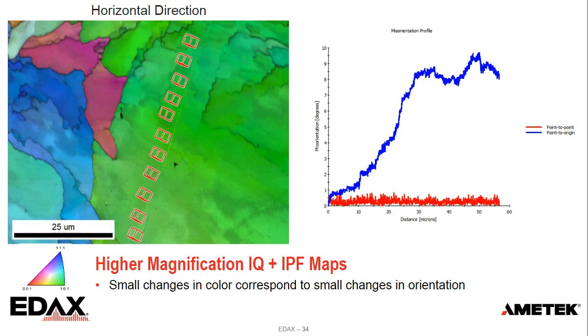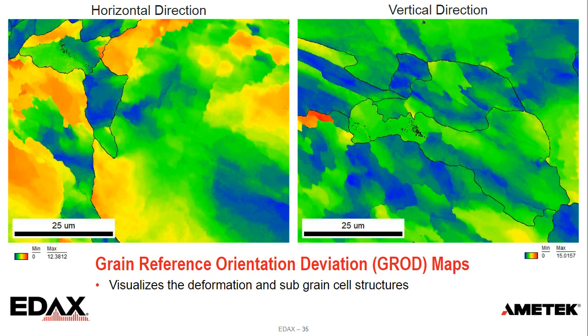The red line shows the point-to-point misorientation. So from point to point, the misorientation is not changing a lot. But if we look from the bottom to the top, there's a cumulative effect of how that misorientation has developed throughout that grain. There's some structure to that misorientation. And we can visualize that with other types of maps.